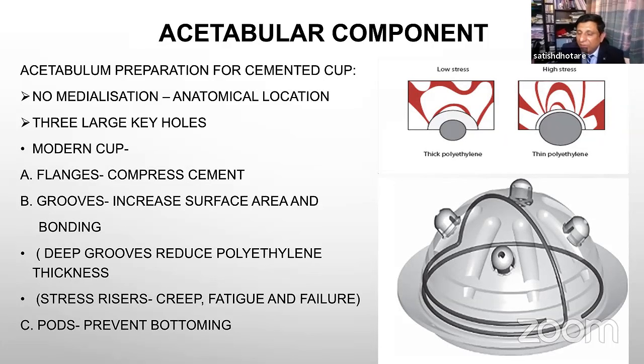And there is no more requirement of exposure of the subchondral plate, because there are many studies which are showing that by exposing the subchondral plate, there is a high risk of necrosis. As we all know, the cement generates heat and it sets by an exothermic reaction, and that heat can cause subchondral bone necrosis, and a fibrous tissue layer will form, and that will be one of the causes of failure for the cemented cups.